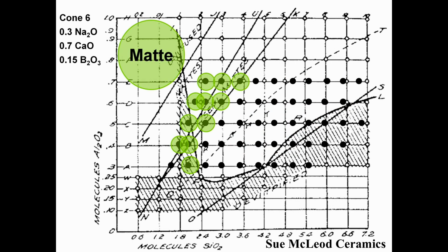This is map number 1 again, showing only the matte glaze results. This left-hand side of the map is where you will find true matte glazes, which are fully melted crystals growing in a glass. This is as opposed to underfired matte glazes that are only matte because they haven't actually melted yet. Often, these are underfired glossy glazes.